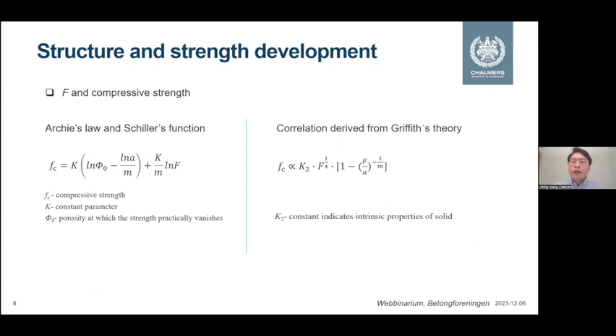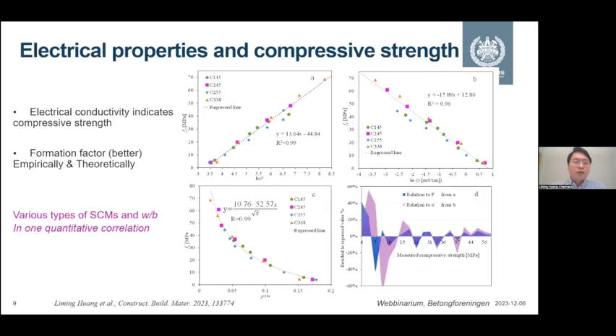So after final setting, what we are caring about is the strength development, as presented here. We try to extract the correlation between the formation factor, or actually between the porosity of the system and the compressive strength. Here I just show the final results, the deduced correlation between the formation factor and the compressive strength. About the details, please check our publication.